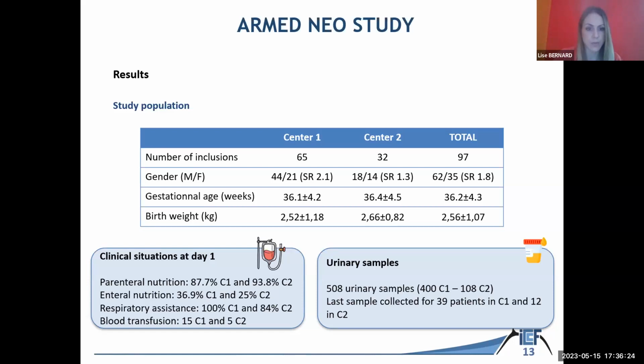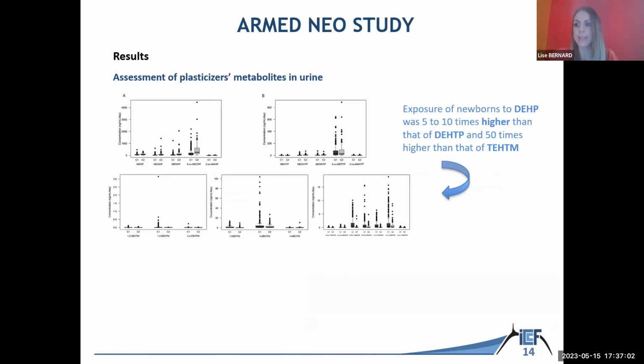The majority, practically all patients, were benefiting from enteral nutrition, 36.9% for Center 1, and you can see the percentages for Center 2. Also, you have respiratory assistance, 100% for Center 1, 84% for Center 2, and 15 blood transfusions for Center 1 and 5 for Center 2. 508 urinary samples were collected, and the last sample was collected for 39 patients in Center 1 and 12 patients for Center 2. Now, the assessments of plasticizer metabolites in urine showed that the exposure of newborns to DEHP was 5 to 10 times higher than that of DEHTP and 50 times higher than that of TEHTM.